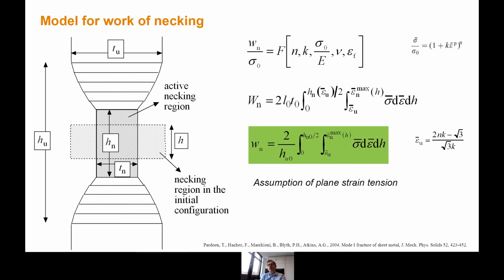But we developed a model for the work of necking, and we developed a model for the work of damage. I will not go into any details, just telling you that the work of necking, you can calculate it by integrating the plastic work that is dissipated in the neck as the neck progresses. So you have to integrate the work from the center to the upper part of the neck. You have to integrate the plastic work to get an estimate of the total work of necking, or work of necking per unit volume. In order to do that, you assume plane strain condition in the direction of the ligament, which is known to be a very good assumption if you run 3D finite element simulations. There is one parameter you need to know.